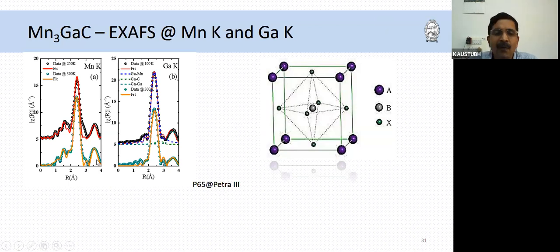And what I want to point out here is this is the fitting to the gallium edge, and you can see that if I use the constraints of the cubic structure and fit the EXAFS signal, I get a perfectly good fit right up to 4 angstroms. And so that tells you that the gallium symmetry, or the correlations around gallium, are in accordance with the structure.